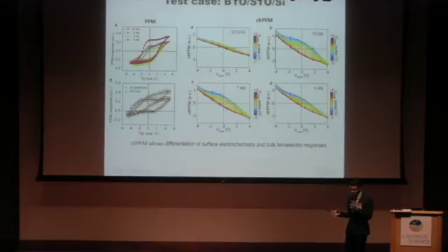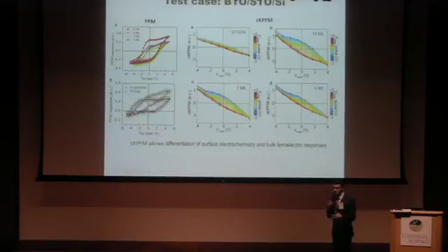And the reason for that is because, number one, there's a noise problem. So if your polarization is less than 2 microcoulombs per centimeter squared, you're not going to be able to see it. That's the noise limit for our technique. The second problem is, of course, that there's obviously a lot of surface problems. So PFM is surface sensitive, and so if you have some kind of dead layer at the surface, or you can't switch the polarization at the surface, like happens in relaxors, for example, then you might come away from this thinking that all you have is electrostatic response, and you don't have a switchable dipole. But that's not actually obviously the case, because you're more interested in the bulk polarization and whether you can switch the bulk microscopic polarization. And so for that, I think what we really need is to combine experiments from complementary methods to try to see what is ferroelectric and what's not.